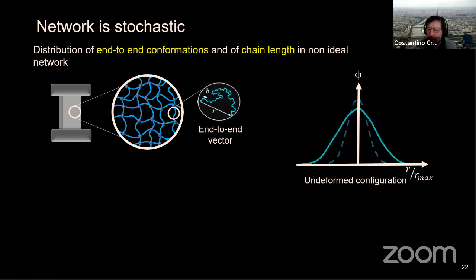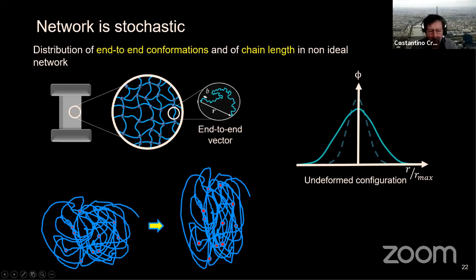When people say these chains are Gaussian, they fluctuate. Of course, with time, we are above the glass transition. So you have the typical Brownian fluctuation. Now, these chains have initial conformation that can be very coiled or pre-stretched. So the chains that are shorter and more pre-stretched, when we actually pull on the sample, will break first. The crosslink points cannot fluctuate too much because they're held in four points. So these crosslink points pretty much deform affinely in this type of bulk elastomers, affinely with the macroscopic stretch, but the chains have a very wide distribution. So you're actually stretching your sample, let's say here vertically, but the distance between crosslink points has this distribution and the short chains will break first.